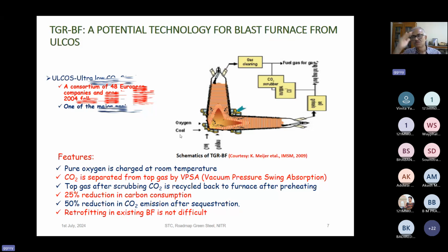The major problem may be the height of the shaft, which may be a limiting factor. Although you are supplementing some amount of the nitrogen by this recycling gas, nitrogen also has a role in the blast furnace, because it increases the heat capacity of the gas. That basically helps supply the heat from the gas to the solid. When nitrogen is not there, heat capacity decreases significantly. But at the same time, since you are recycling the gas, that increases the heat capacity of the gas. But this should be commensurate. If it is not, then maybe you have to look into the height of the furnace. Or, in place of oxygen, people can think about oxygen enriched air blast. That can also improve the heat capacity of the gas if it is reduced.